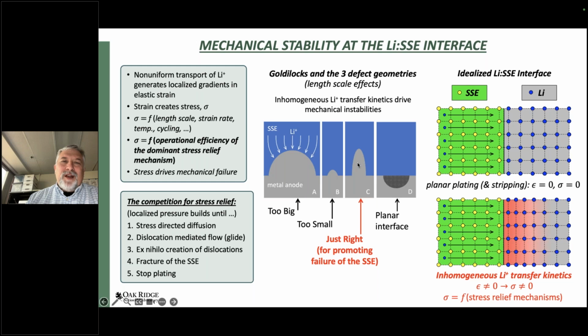The key issue is that defects in between those two limits are too small to have a high probability of finding mobile dislocations, but too big for self-diffusion to provide efficient stress relief. Under those conditions, the pressure can climb, potentially as high as 100 MPa or more. Those stresses are potentially capable of enabling failure in the separator, fracture of the separator.